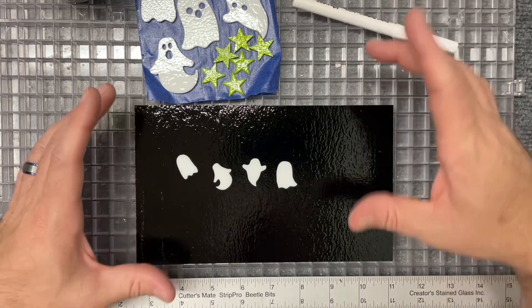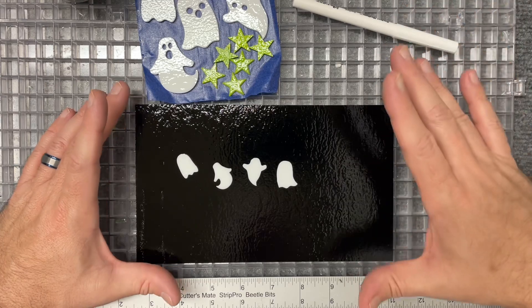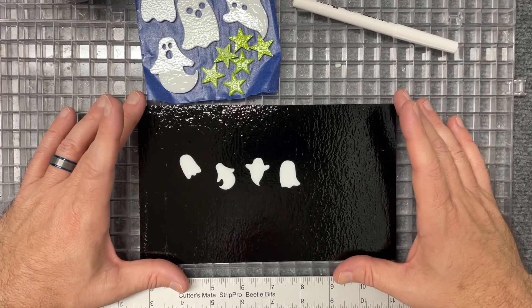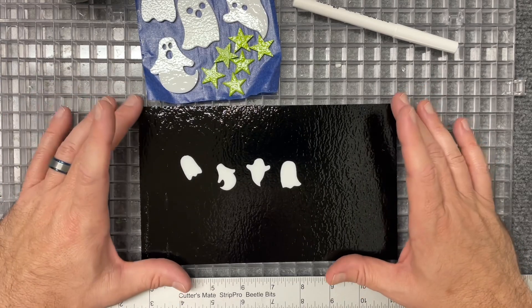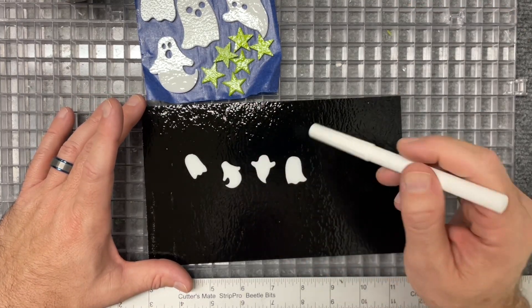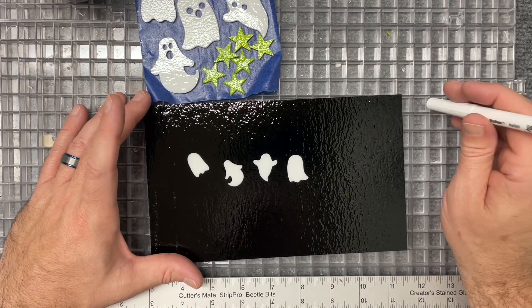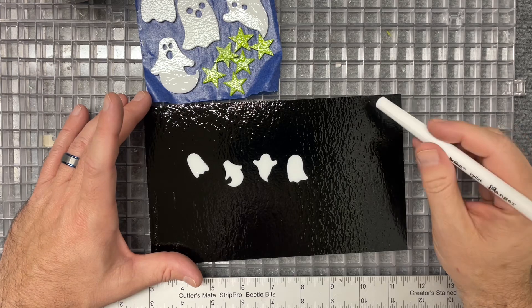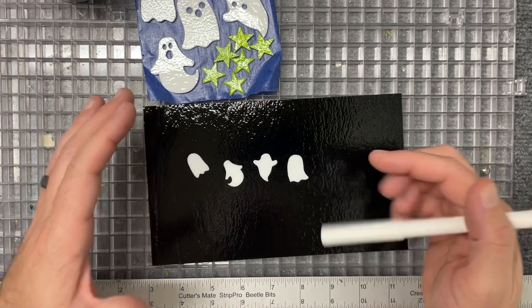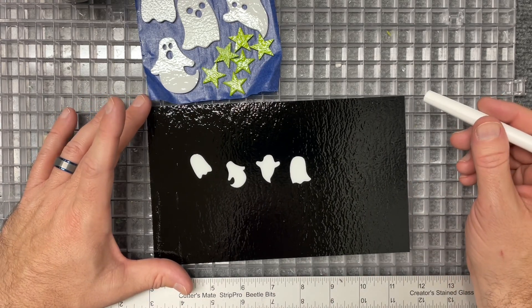What I'm playing with here is I want to do a full fuse on this piece because I've got other things going in for full fuse as well and I'm filling up the kiln. But I also want to slump this later in a unique way that I think would be better with a full fuse. The problem with full fuse and some of these water jet cuts is they kind of bleed out and get too fuzzy around the edges — round off too much and you lose the definition. So I'm going to build this panel and then flip it upside down to fire it so that I keep some of the definition around these shapes.